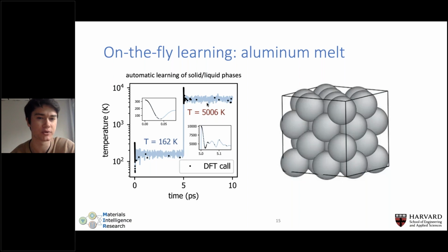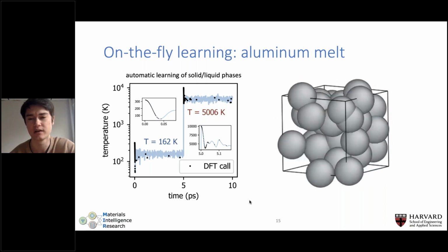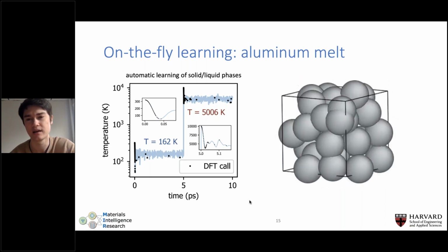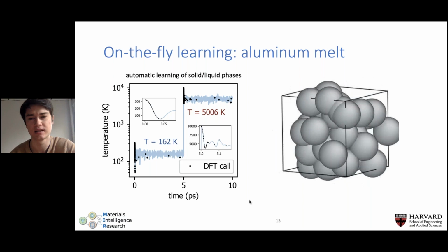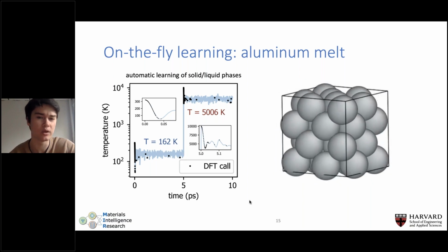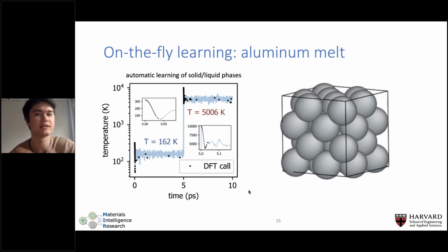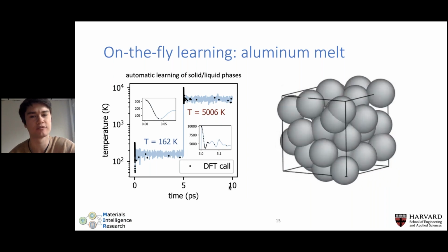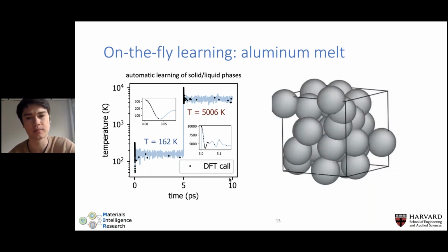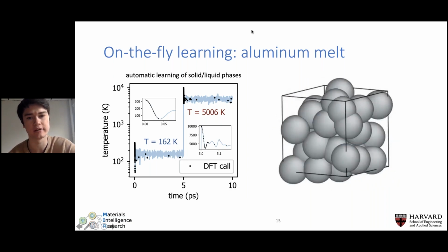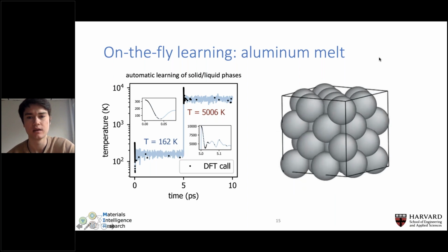But then as the simulation proceeds, again, we need fewer and fewer calls to DFT. And here, just to give you a visual, this is the full on-the-fly simulation. We start in the FCC phase, and then we melt the crystal. We essentially just wanted to show we're able to detect new phases, and we can iteratively improve the model in a single molecular dynamics simulation.